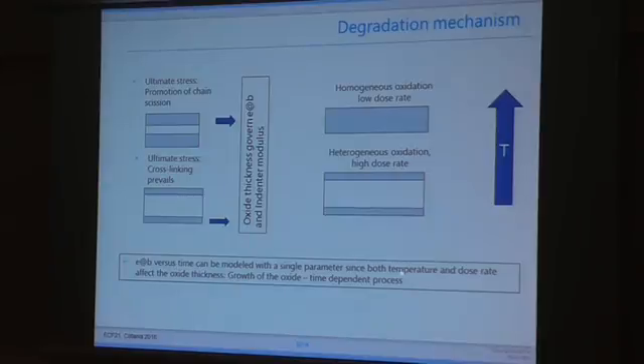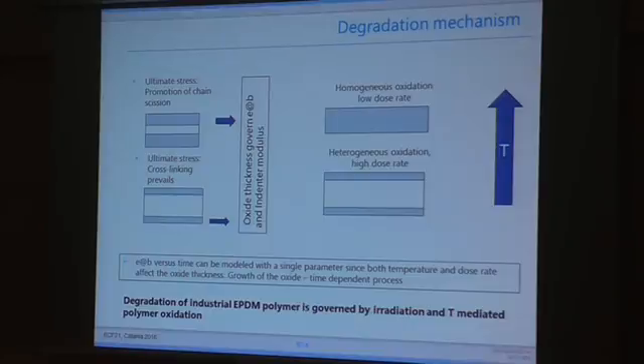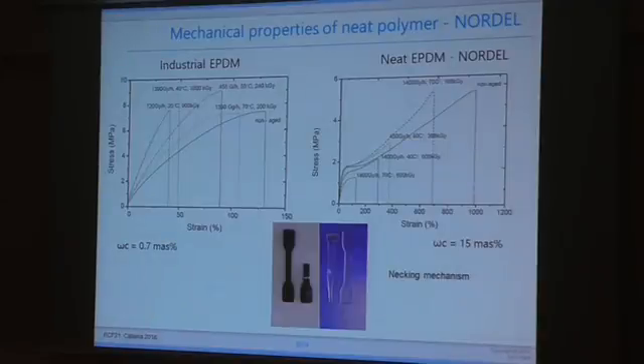So, in order to explain the modeling, elongation at break versus time can be modeled with only a single parameter, because both temperature and dose rate affect the oxide thickness. So the growth of the oxide is time dependent. And moreover, we found that for industrial EPDM polymer, oxidation seems to be the main degradation process. Now further, we will compare our data with the data for the neat polymer.